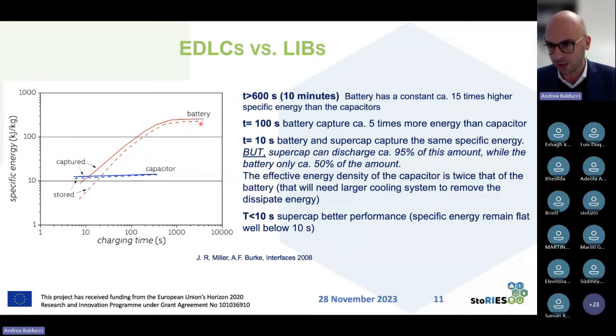His energy is too low, simply. When you are then reducing the time to 100 seconds, there is still a considerable difference, but still the gap becomes much lower. It's not anymore 15 times, but it's 5 times. When then you move to 10 seconds, here it becomes very interesting, this comparison, because what you can see is that basically the capture energy of supercap and battery is basically the same, is where they are crossing.